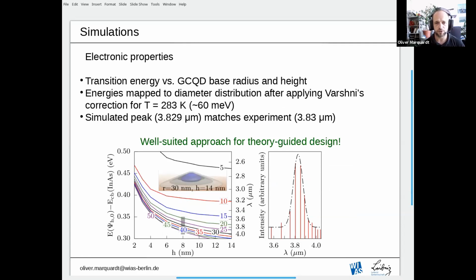We have looked at transition energy as a function of the graded composition quantum dot base radius and the respective height. So the base radii can be seen here in these numbers on the corresponding lines, and the heights are down here. And what you see here in the inset is basically how a hole state, that's the blue thing here, looks in such a graded composition quantum dot for one of the typical systems. And we have then taken a sample of our simulations, which is this gray frame down here, which pretty much matches the values we know from experiment in terms of diameter and height distribution.